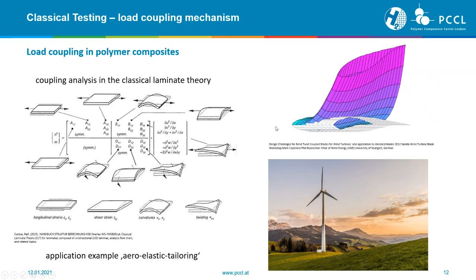When we now think of classical tensile testing, then nowadays more and more smart materials have come up for different applications. And what is already applied for different composite materials to achieve this load coupling, for example, for some wind turbine blades, or to have these aeroelastic tailored applications, we've also tried to implement for soft materials, which means that we replace the resin with the silicone and try to introduce some load coupling mechanism directly in soft materials to combine both, for example, distinctive tension-twist coupling.